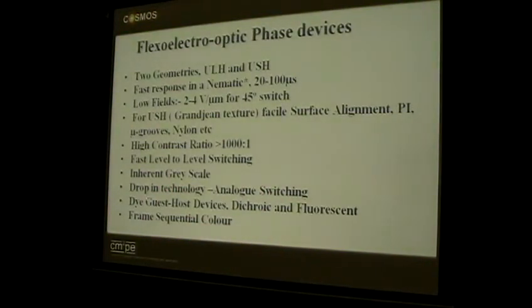What I haven't talked about today, but you can actually, when you make those bimesogens, and you'll see some structures tomorrow, maybe later on today if you get the time, you can put dyes into the bimesogens. And in fact, the nonlinear optical material I highlighted, the nitrostilbene, is actually a dye. And we use that in the lasing devices, where we have a dye at one end of our bimesogen, and a dielectric moiety at the other end. Okay? And then you can make all sorts of nonlinear optic, dichroic, absorbing, fluorescent devices. And the real key, and what's important for energy saving, is frame sequential color. That's what I said right at the beginning. You can switch so fast that you don't use color filters anymore, you use LEDs. You can use bright LEDs with very good optical efficiencies. So you throw the color filters out. And what I'll show you with the blue phase systems, you can even throw the polarizers out.